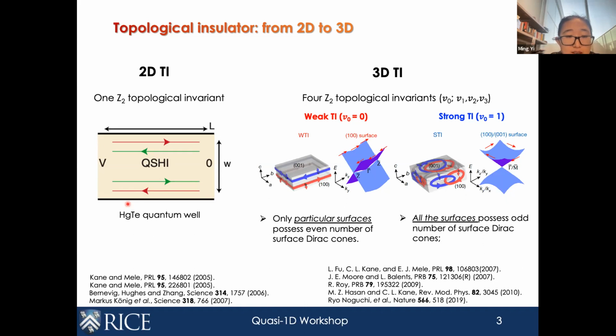The naming convention for a weak TI is because originally it was conceived that the topological states in the weak TI are quite fragile, because if you have even numbers of Dirac cones, under some sort of perturbation, such as disorder or dimerization, you can easily gap out the topological surface states, which makes it indistinguishable from a trivial insulator. But now, due to all the great work in theory, we understand that this sensitivity is actually a benefit, because this makes the weak TI systems much more tunable, for realizing, for example, higher order TIs. So it's really interesting to look for systems that are weak TI.